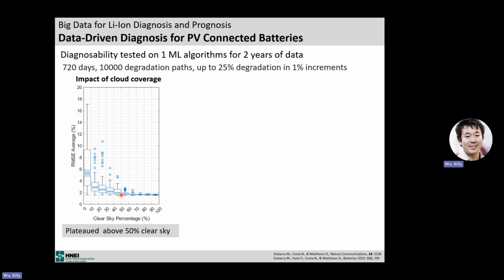But you can see that above 50% clear sky, the error kind of plateaued, and we have almost no more outliers. So that showed that for 50% or more clear sky, which for us is 1 day out of 5, we can diagnose the cell perfectly. And that's enough. Remember that your cell is supposed to last a decade.